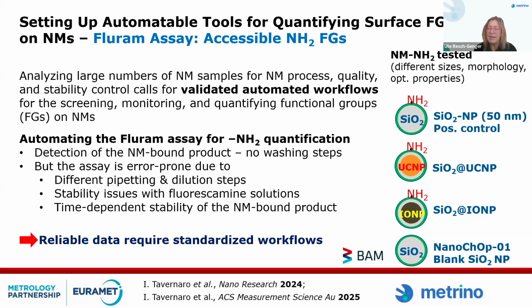And the reason why it can be easily automated is because you detect a product which is bound to the nanoparticle surface. So you don't have washing steps, which make automation more complicated. But this assay is error-prone, so you have pipetting and dilution steps, and stability issues, so the product which you detect is not stable for a long period of time, maybe for 3 hours. And this implies that you really have to have a standardized workflow or protocol for the assay.